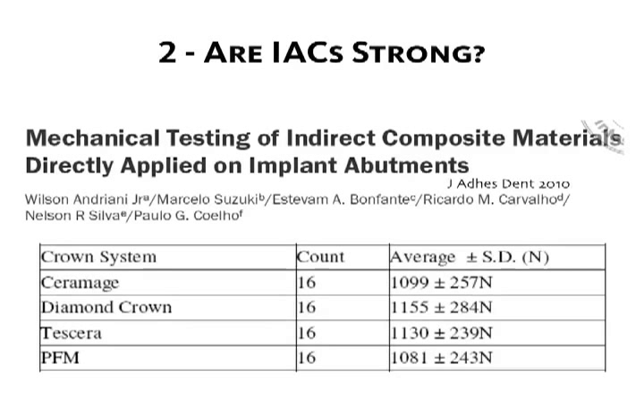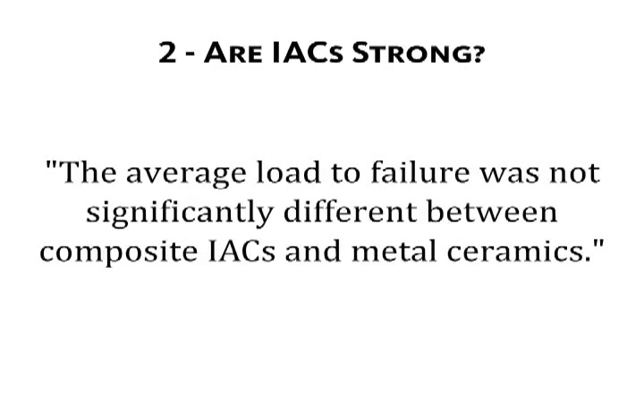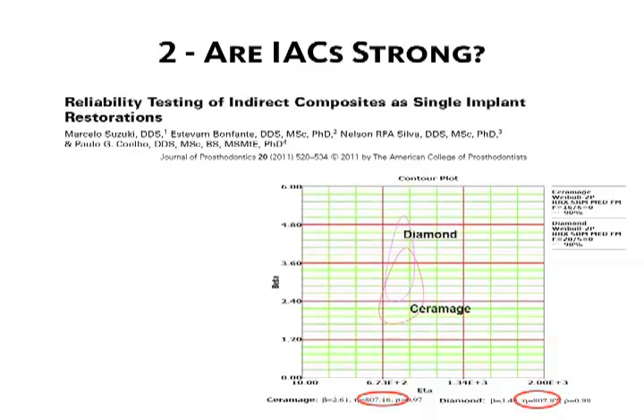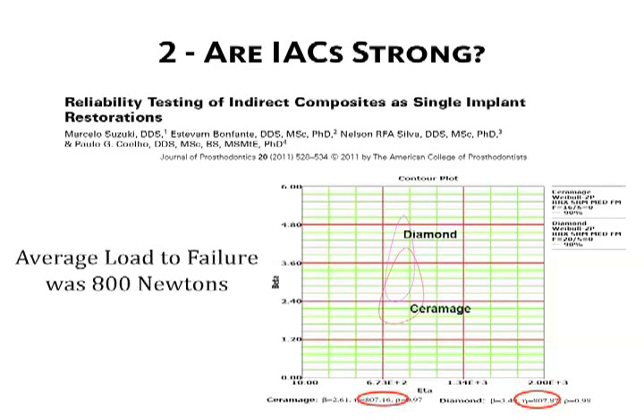Subsequently, the load-to-failure behavior of IACs made of several different composites was compared to metal ceramic. The results showed that the average load-to-failure was not significantly different between composite IACs and metal ceramics. Under fatigue loading, IACs made of two different composites showed that the average load at which they failed was around 800 newtons, and as you see from the contours overlapping, they were not statistically different.